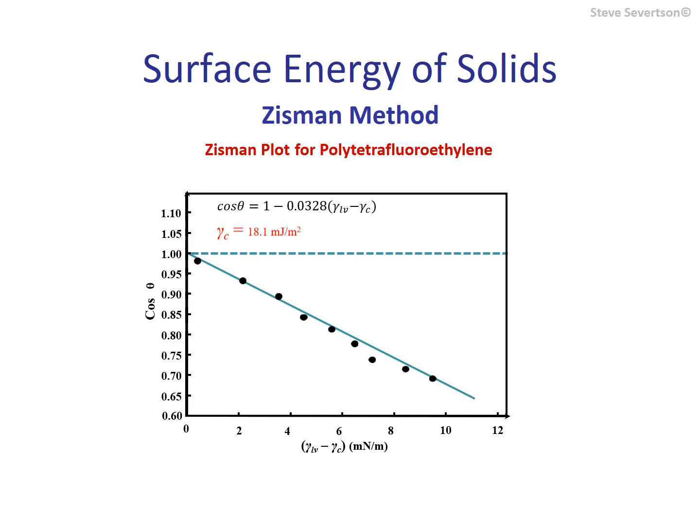However, published studies demonstrate that the approach can be quite sensitive to relatively minor changes in solid surface compositions. The accuracy of this method is strongly dependent on the accuracy of the surface tension of the liquids and the quality of the static contact angle measurements. This approach is believed to work best for low-energy surfaces for which purely London forces contribute to the surface energy — that is, low energy solids and alkane solvents.